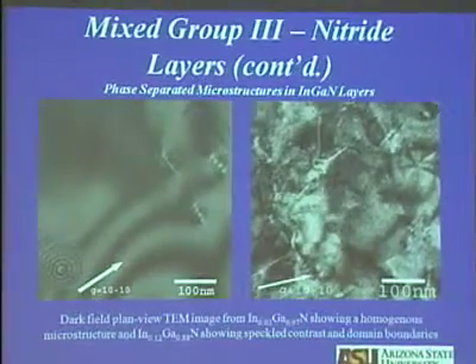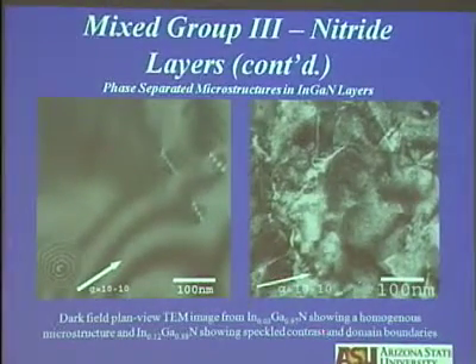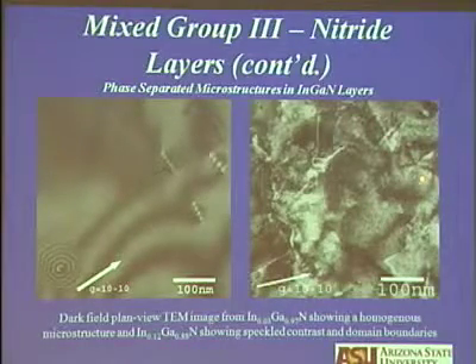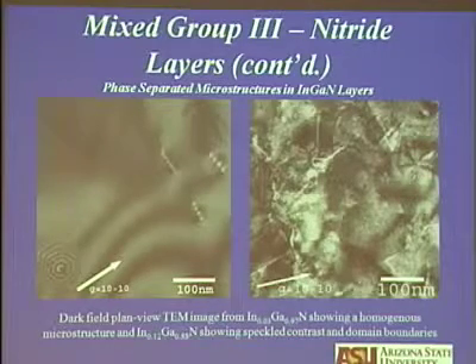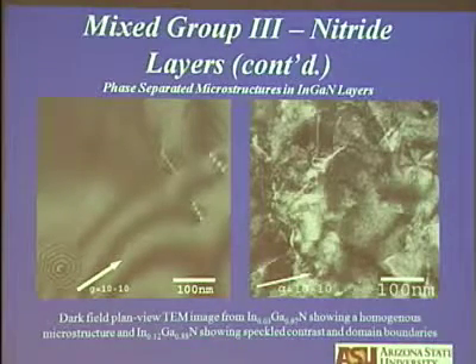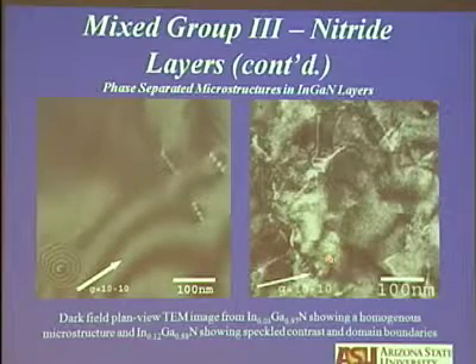At 3%, if you have a standard, those who are familiar with the microstructure, there are no modulations present in this structure. But look at this case, it's 12%. You see speckle structure, you see the stripe structure, and you see the boundaries. So there are 3 features I need to explain: what the stripe structure is, what the speckle structure is, and why you have the boundaries?